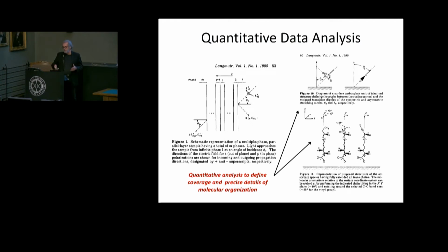And this is a diagram showing the more detailed structural model with all the details that have to go into doing that, and attributes of structure that came out of that first foundational study. For example, whether or not the carboxylate group bonds to the interface via a structure that's bidentate with C2V symmetry, or a distorted version of that, which you get from the characteristic intensities of the symmetric and antisymmetric carboxylate stretching vibrations.